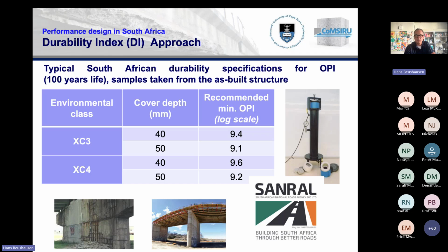So you can see here the SANRAL specifications that allow you, for a certain exposure environment, to trade off cover depth versus concrete quality. So for example, if you're in the most severe environmental exposure, XC4, and you work with a cover depth of 40 millimeters, then the typical minimum OPI that is required is 9.6. But if you can increase your cover to 50 millimeters, you can allow a lower concrete quality indicated by a lower OPI value. So this approach also allows us to basically combine the concrete properties with the cover depth to come to the best solution for this particular structure.